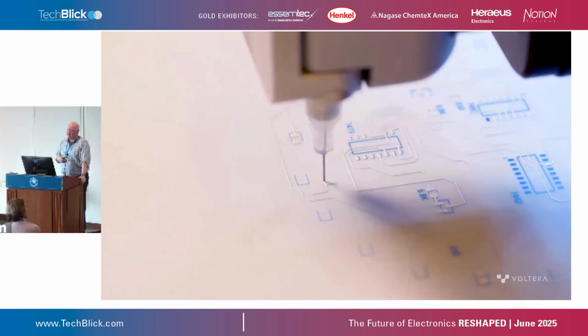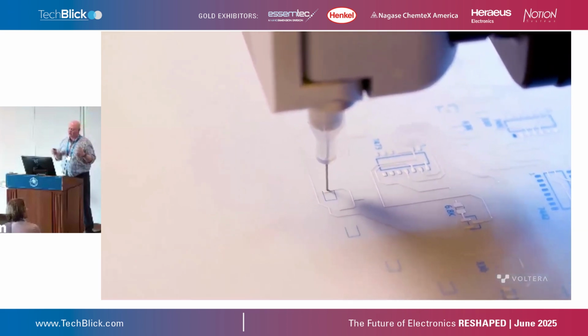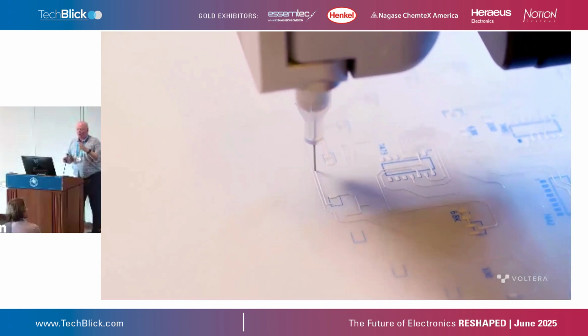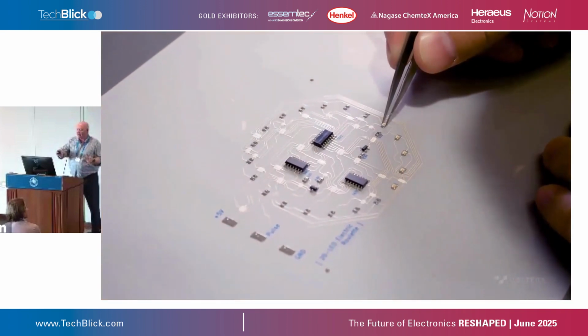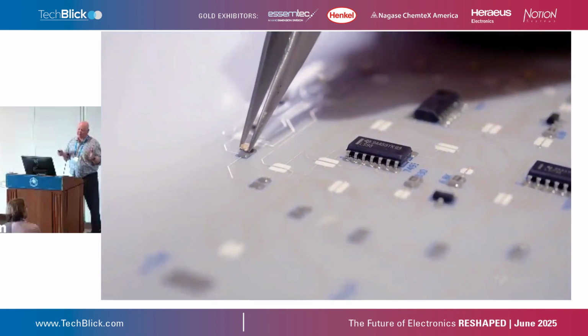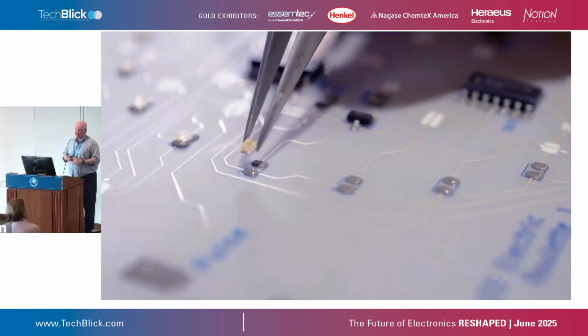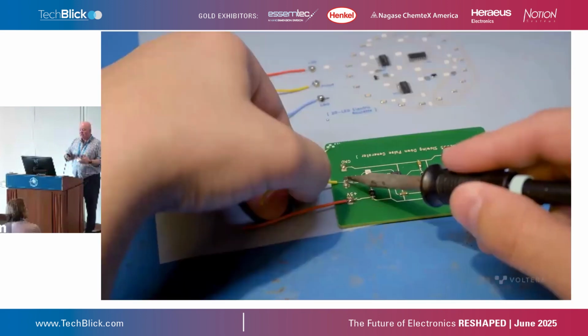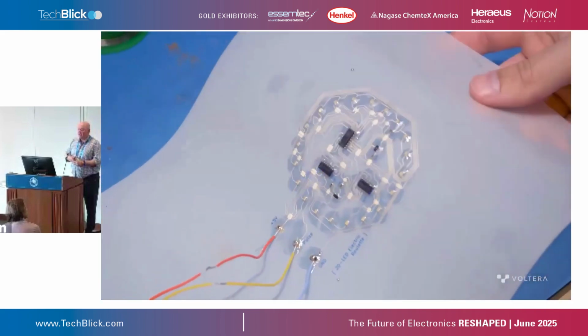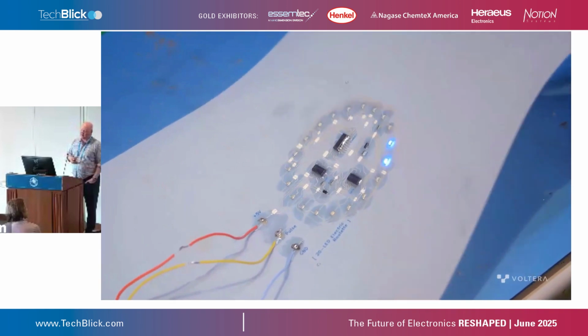We have worked closely with Voltera. They build a very nice prototyping piece of equipment where they can take production-ready materials and dispense them for prototyping, and use those same materials in production. And this is showing a really nice roulette board. It's like a 1.5 layer, so it's got jumpers in there. And then they're placing components on the solder. Even hand soldering to that polyester circuit at about 160 centigrade. And they do put Glob Top on top just to secure those larger components, etc. Get a nice circuit. So this is prototyping.